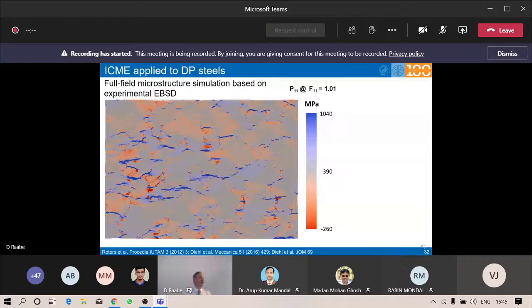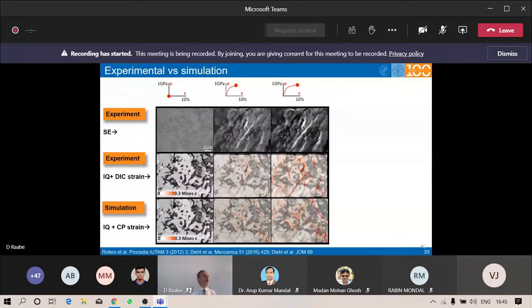But interestingly, you see even compressive stresses, which happens when two very hard areas are moving together by the constraints, and they can set local regions even under compressive load. So this is something that you get out of a more complex microstructural landscape, such as encountered in many complex steels. When you now, however, go stepwise through each of these volume areas and study in detail the quality of